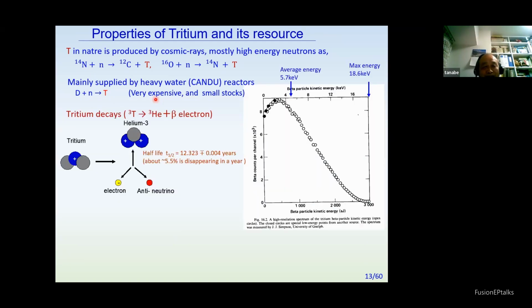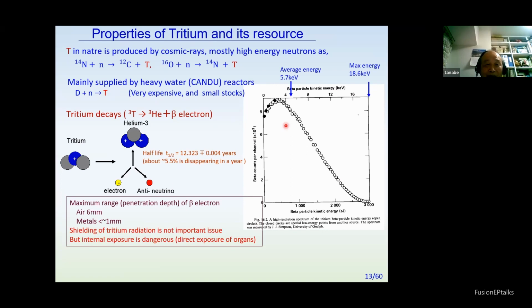And tritium decays to helium-3, emitting beta electrons, with a half-life of roughly 12 years. The energy profile of the emitted electron is like this. The average energy is 5.7 keV, maximum 18.6 keV. This is very low. So the maximum range of a beta electron is only 6 millimeters in air. In metals, this is micrometers, I'm sorry, less than 1 micrometer.